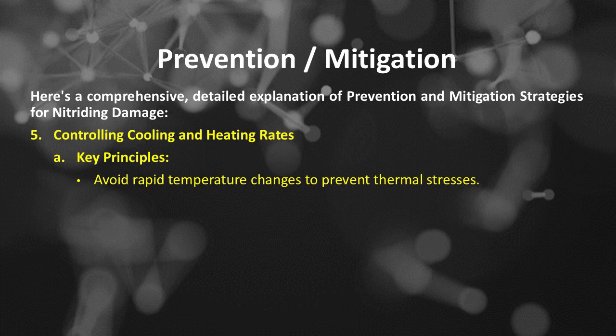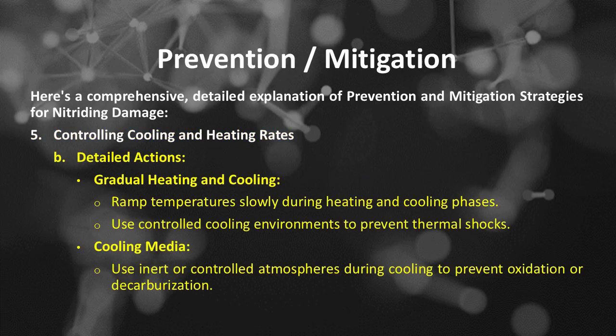Number 5 of prevention and mitigation strategies for nitriding damage is controlling cooling and heating rates. The key principle is to avoid rapid temperature changes to prevent thermal stresses. Detailed actions include, first, gradual heating and cooling: ramp temperatures slowly during heating and cooling phases, and use controlled cooling environments to prevent thermal shocks. The second is cooling media: use inert or controlled atmospheres during cooling to prevent oxidation or decarburization.